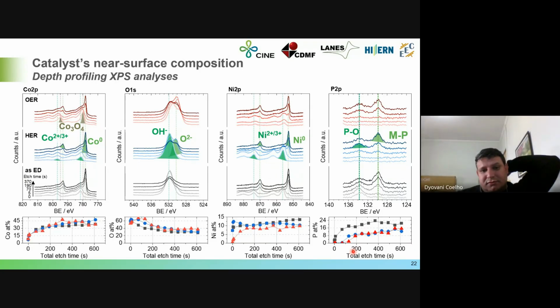So we don't have phosphorus on the surface for the hydrogen evolution reaction and for the oxygen evolution reaction, which means that it's just putting the catalyst inside the alkaline medium and the phosphide is just dissolved. But underneath we can see the characteristic peaks, the binding energy for the metallic phosphide bonds here, for the hydrogen the same, and for the oxygen evolution reaction the same, and for the phosphates, the binding energy of the phosphorus oxide here, for the oxygen evolution reaction, for the hydrogen evolution reaction, and even for the catalyst as deposited.